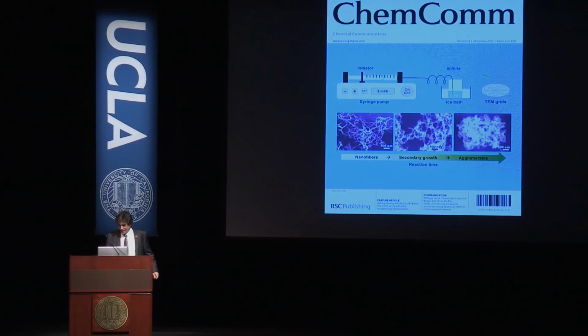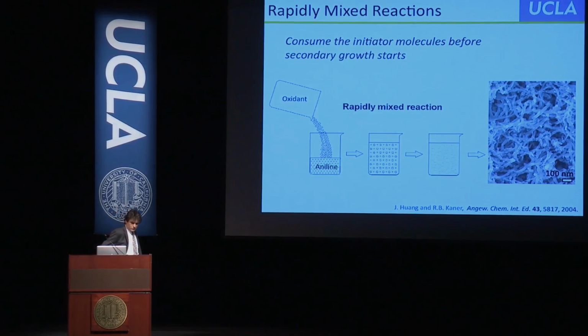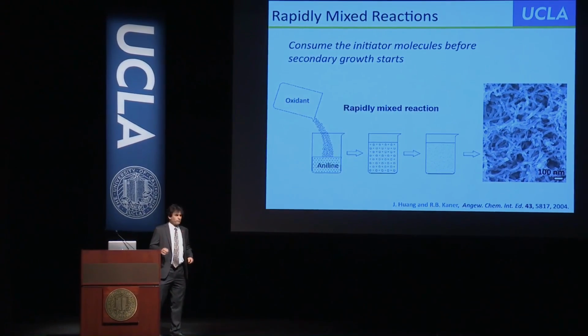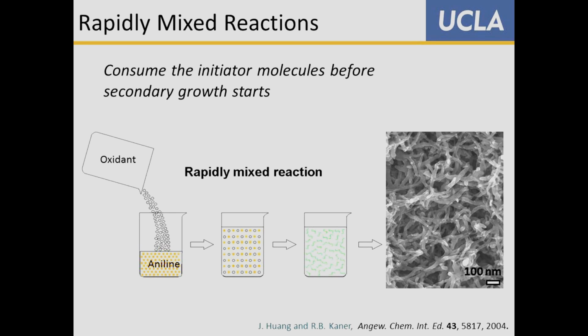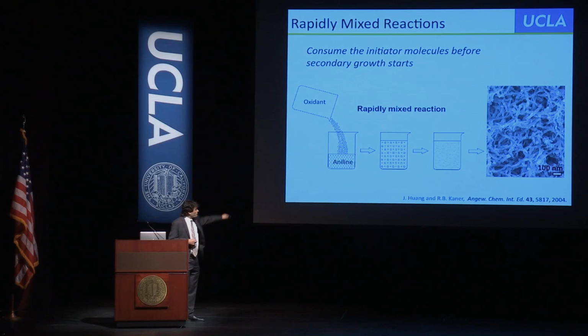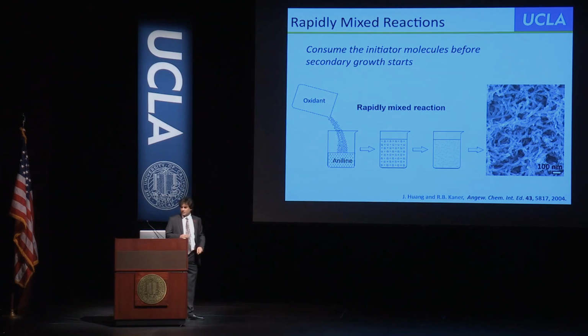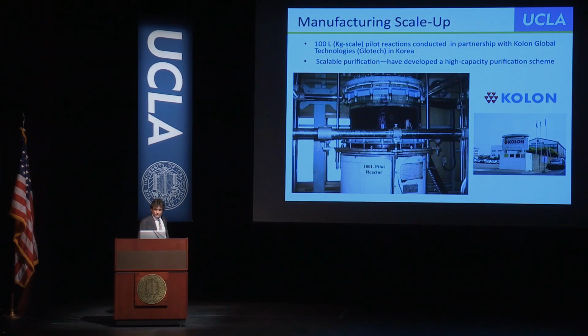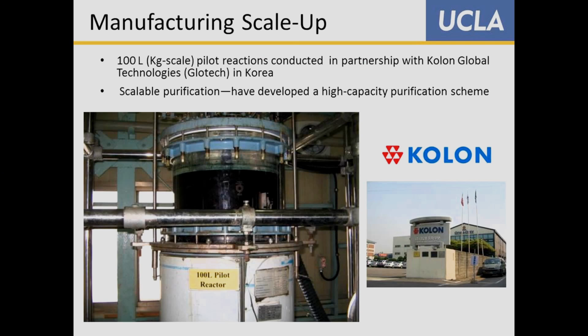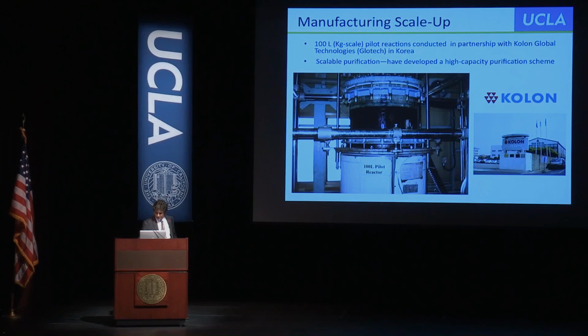However, after we did this, we realized that we could make our nanofibers disperse in water. And in fact, I'll even show you we now know how to melt them. We discovered that process too. But it led to this much simpler process. And the idea is if we take oxidant and aniline and throw them together in a stoichiometric amount at room temperature, we use up all the aniline, form nanofibers, they can't agglomerate. And so this process makes nanofibers in as large an amount as you want. And I can say that because we worked with Korean nylon, known as Kolon, and they scaled up our reaction with our help to a 100-liter pilot plant reaction. And so you can do this and you can make as much of this material as you want.